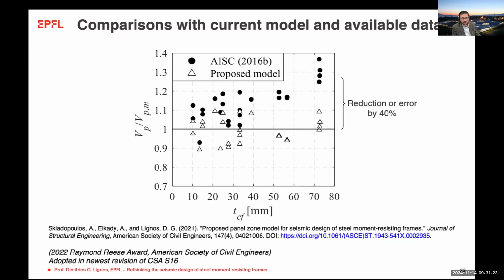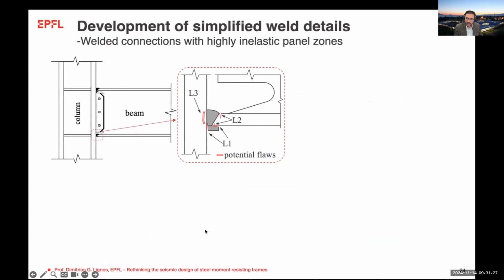Now, a couple of other things that we were interested in are related to fabrication detailing. In particular, when I'm looking at the way we are fabricating welded joints, as I mentioned before, in this region we usually use a backing bar so that we can complete the complete joint penetration weld. Because of the detail here, I have locations of potential flaws that I'm marking here as L1, L2, and L3. Assuming that you are using the new construction materials that we use today, L3 should not be a problem because this is related to through-thickness properties of the flange. So the focus is on L1 and L2, which would be potential flaws because of the welding process.